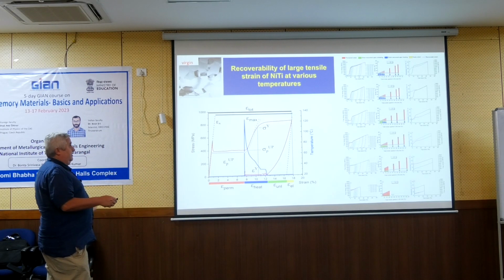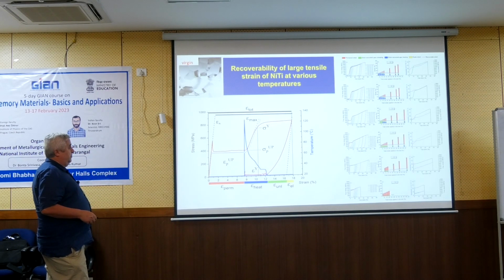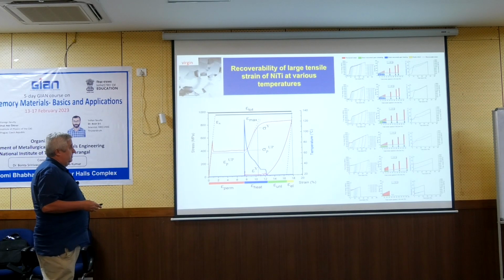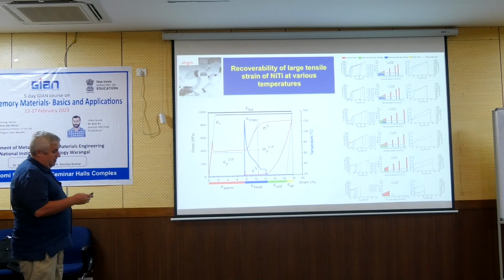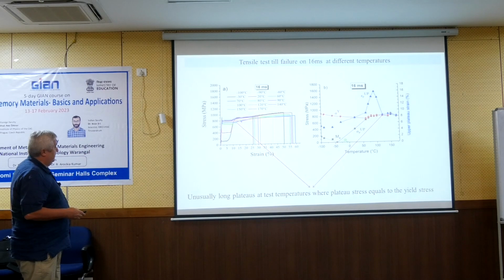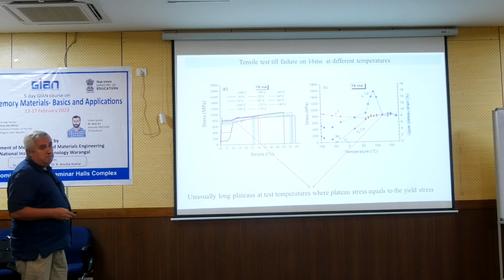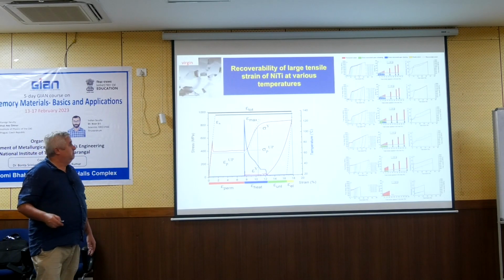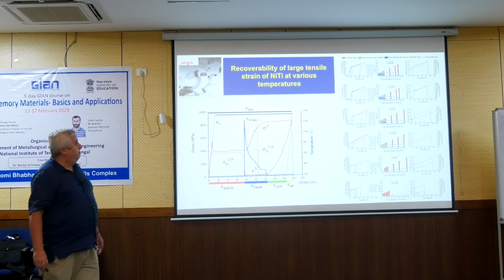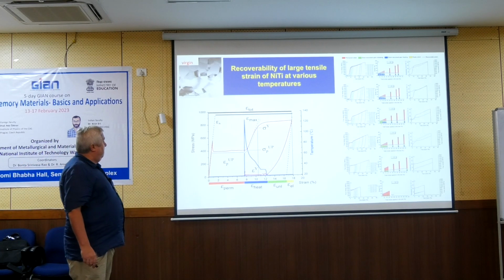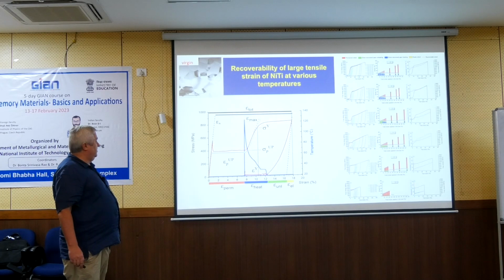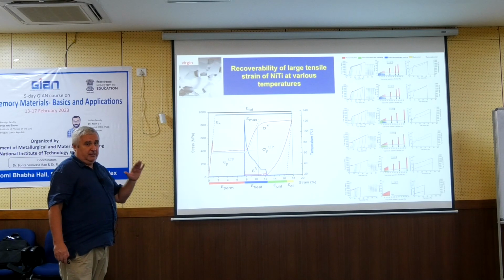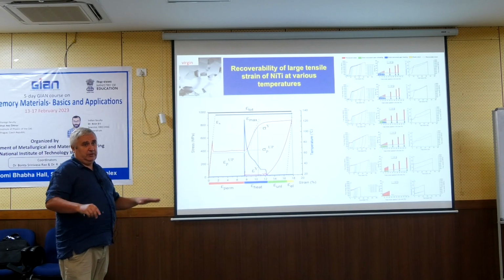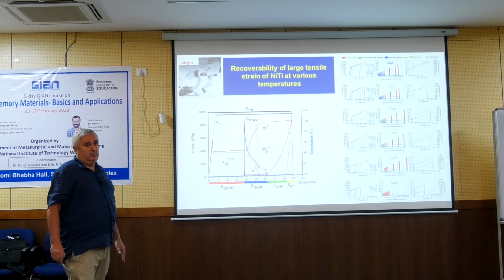So when the cubic to monoclinic transformation occurs during loading, you have this type of recoverability of strains. Previous cycle? So is this for the initial cycle or the stabilized cycle? This is the first, initial one, one cycle on each wire. We heat treat and deform and destroy. Very first cycle, yeah.